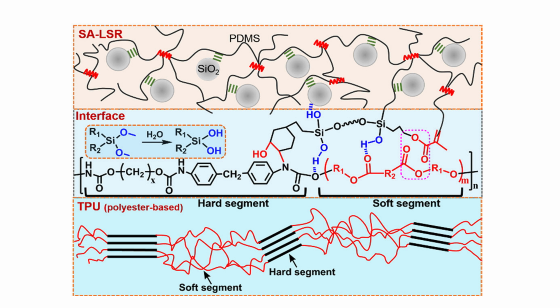When a UV photon is absorbed in a silicone coating in the presence of water, siloxane or alkoxy-silane bonds are hydrolyzed with the formation of silanol and carbonyl groups, which are capable of reforming siloxane or alkoxy-silane structures. In this way, the coatings can absorb high-energy radiation in the presence of moisture without suffering irreversible damage.